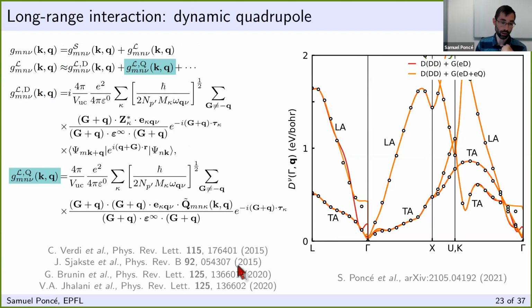Something that was discussed very recently, in 2020, is the fact that in order to describe those discontinuities, we need to also add more terms in this long-range expansion. This is the quadrupole term, which has this form that is given here. Notice that in this case, we have QQ divided by QQ. So we have something that does not diverge, but it will be direction dependent. It will come with a different value as you approach gamma. Now, as you can see, I have applied this strategy of removing and adding quadrupole on the electron-phonon matrix element, but not on the dynamical matrix. And you can see that the interpolation is therefore not perfect.